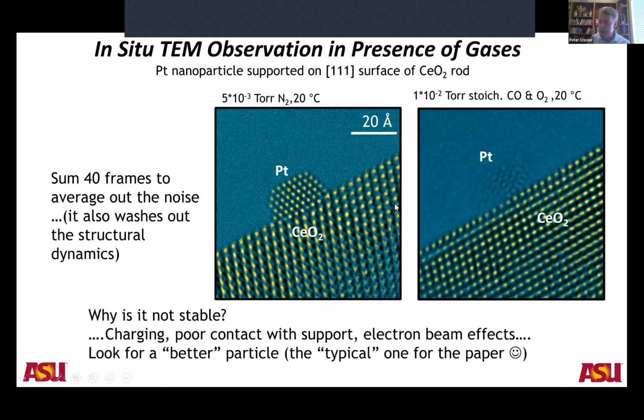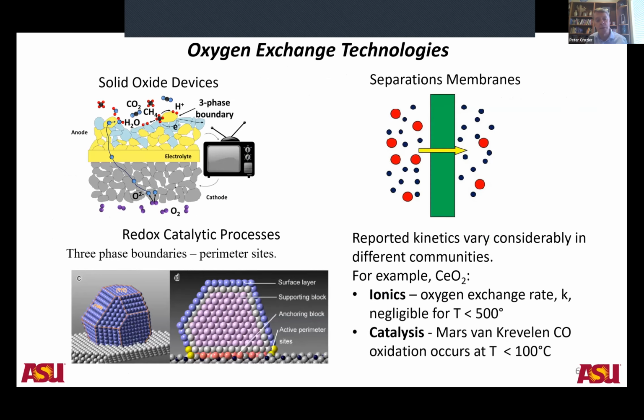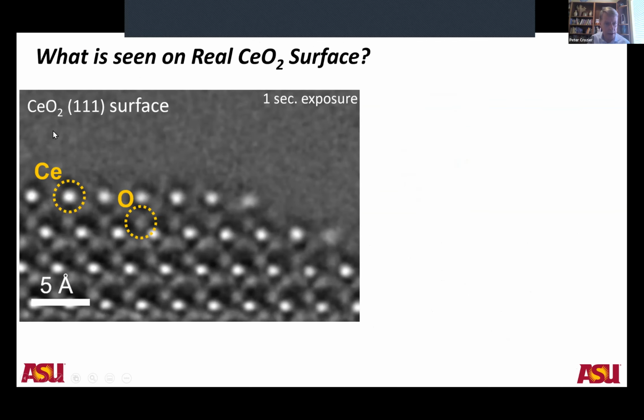At about the same time, we were working on oxygen exchange technologies and electroceramics, looking at oxygen exchange transport through bulk oxide ceramics and also exchange at the surface. One of my students, Ethan Lawrence, was trying to look at the defects on the surface of cerium oxide. This is an image of cerium oxide, a negative CS image in the Titan. The very bright dots you see here are the cerium atoms. The oxygen atoms are a little bit fainter, but they are present, and you can even see the oxygens up at the surface here.